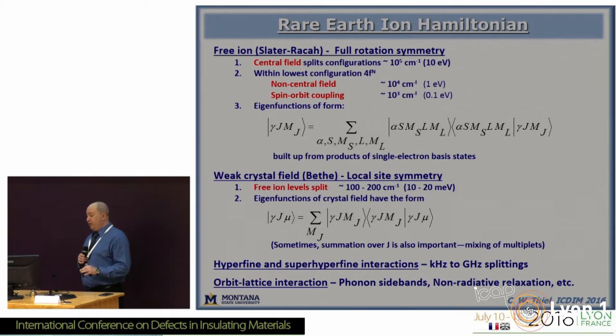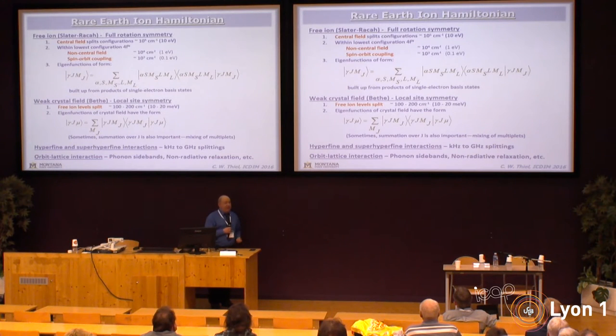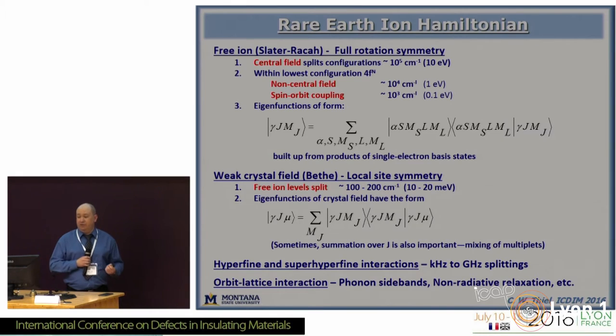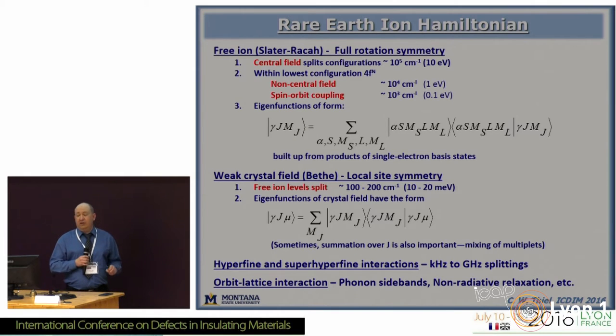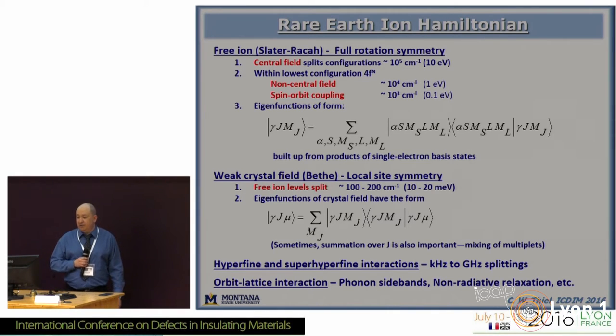If we take a step back and think at the basic level about the nature of the electronic states in the rare earth case: first, you think about the traditional atomic physics picture, where you have the central field splitting the configurations, then the electron-electron interaction, as well as spin-orbit coupling which splits the Russell-Saunders multiplets and then mixes those multiplets. In the end you have things that look like atomic wave functions labeled by LSJ quantum numbers, although only J is a good quantum number because of the significant spin-orbit coupling.